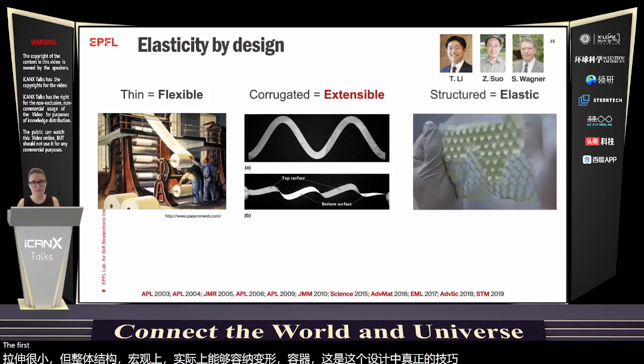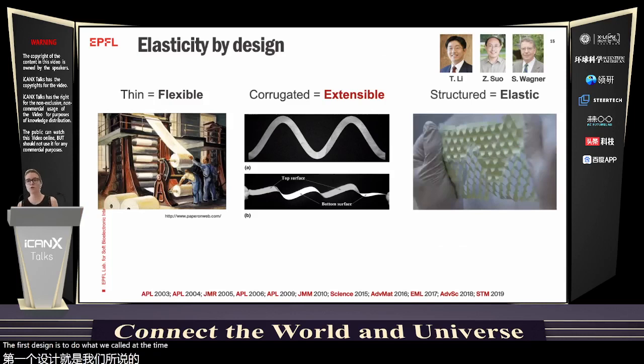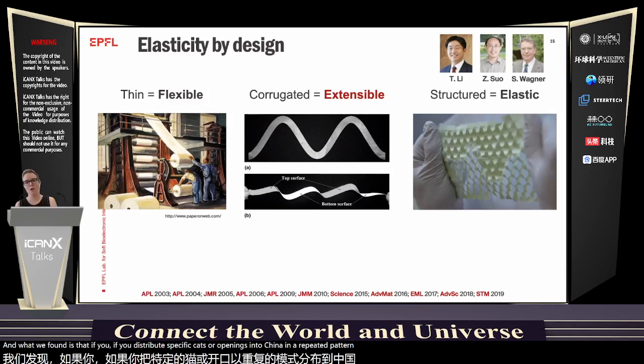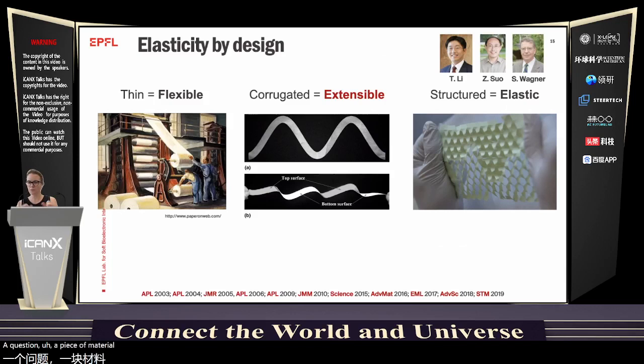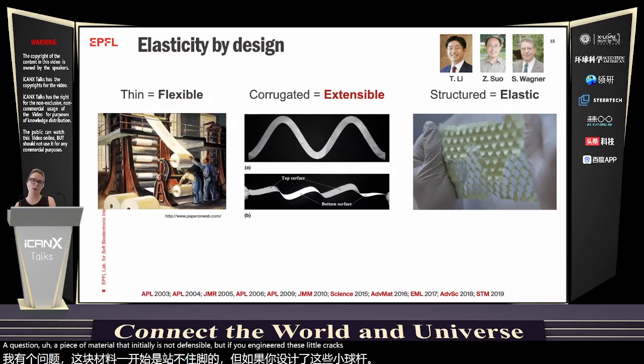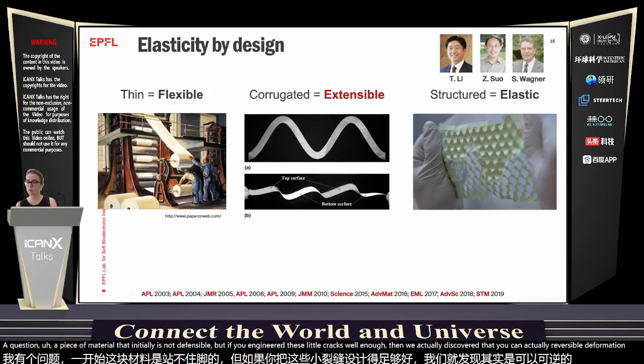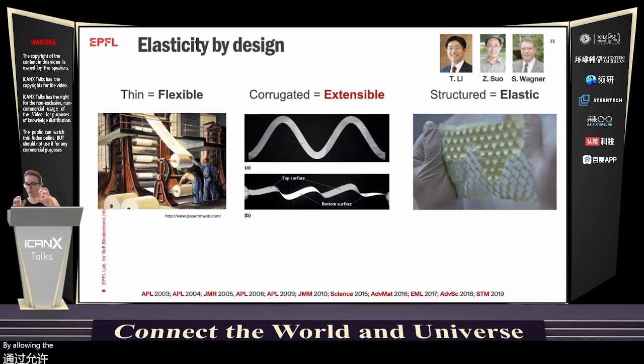The third design is what we called at the time structuring or microstructuring. What we found is that if you distribute specific cuts or openings in a repeated pattern across a piece of material that is initially not deformable, and you engineer these little cuts well enough, then you can reversibly deform the structure by allowing the ligaments of the structure to tilt out of the plane, and therefore have this extension enabled. So that's the third concept.